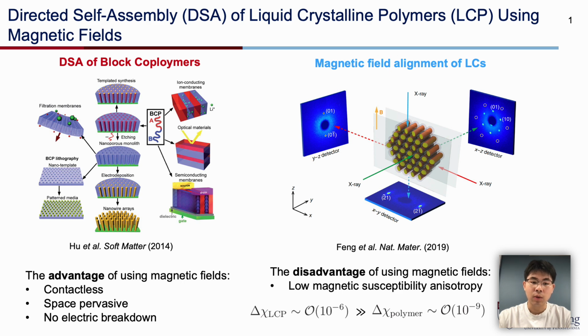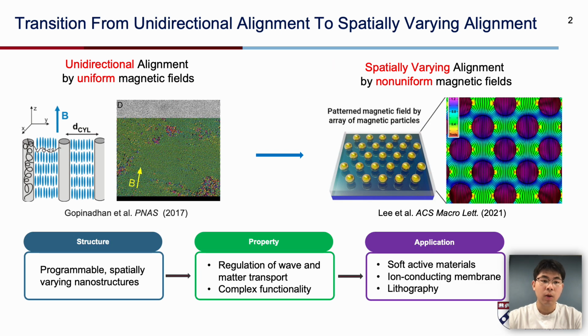So we choose to use liquid crystalline polymer, which has a much larger susceptibility and anisotropy than a normal polymer with random coil nature. A lot of work has been done on unidirectional alignment by using uniform magnetic field. And now we want to change from unidirectional alignment to spatially varying alignment by using non-uniform magnetic field. We envision that by patterning the magnetic field with arrays of magnetic particles, we can make programmable, spatially varying nanostructures, so we can regulate the wave and matter transport within the materials and maybe provide some complex functionality. We believe this can be useful in soft active materials, in making ion conducting membranes, or doing lithography.